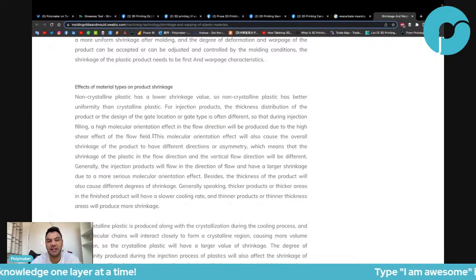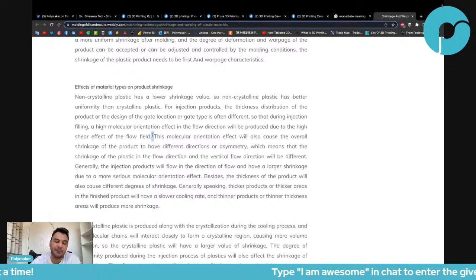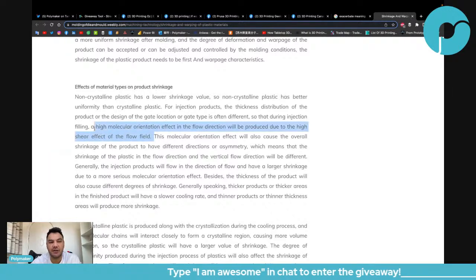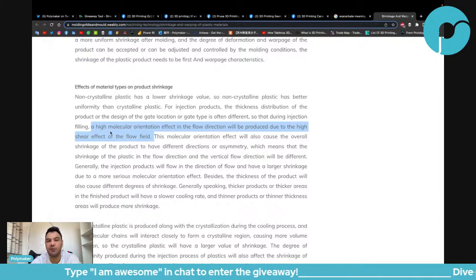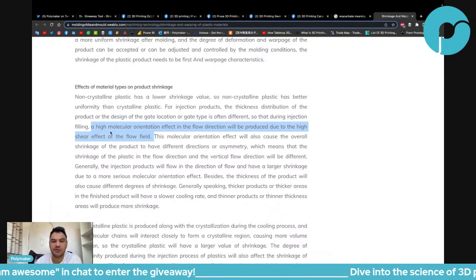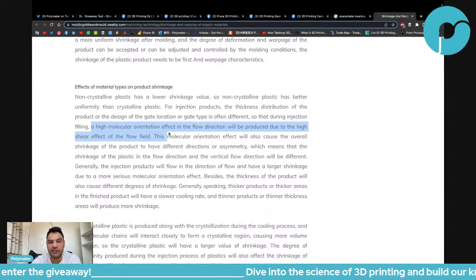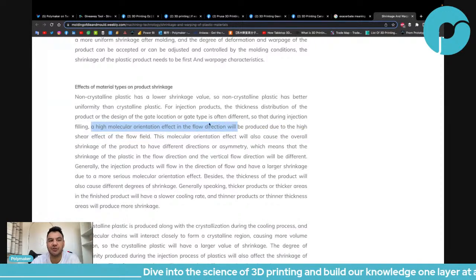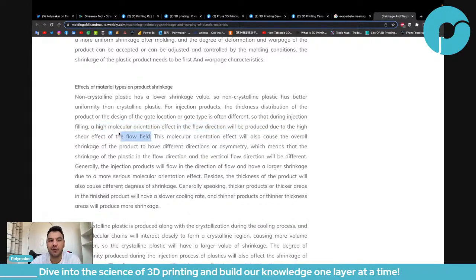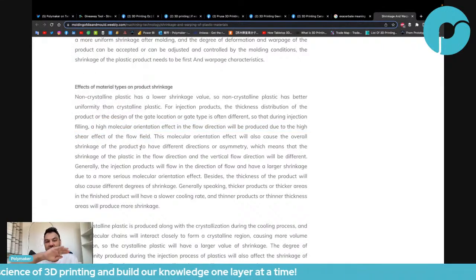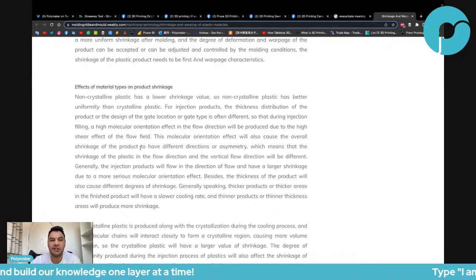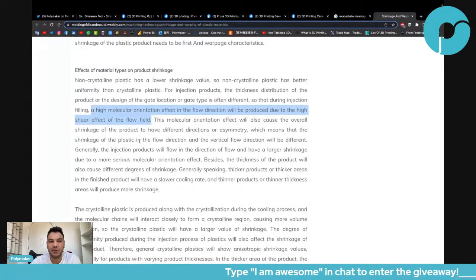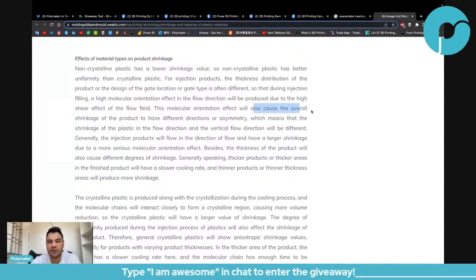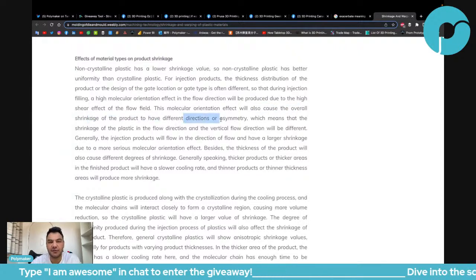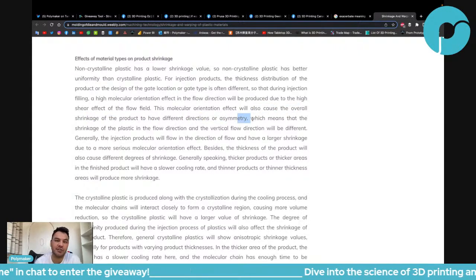Well, the good thing is that they explain the elastic deformation pretty well, right? That's exactly the cause of warping. In my opinion, the main cause of warping comes from this. The high molecular orientation effect in the flow direction will be produced due to the high shear effect of the flow field. Okay, so that's the velocity curve that we talked about in the nozzle. That's for me the main reason why the polymer is stressed when you're printing. This molecular orientation effect will also cause the overall shrinkage of the product to have different direction and asymmetry. Yeah, and it's the same in 3D printing.